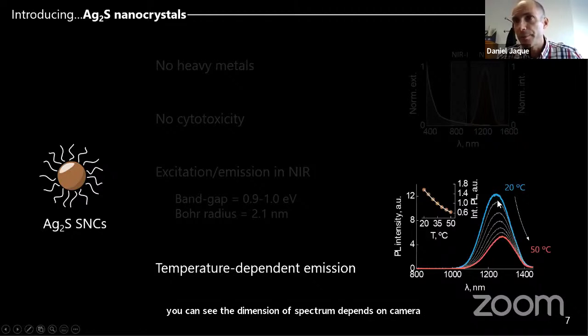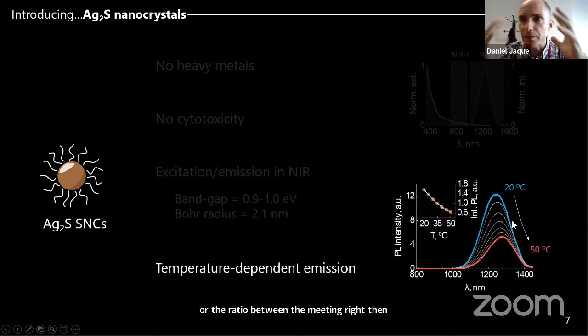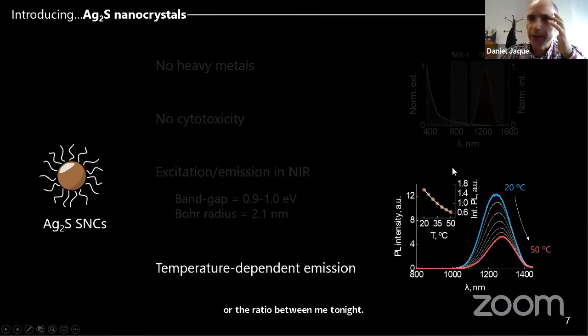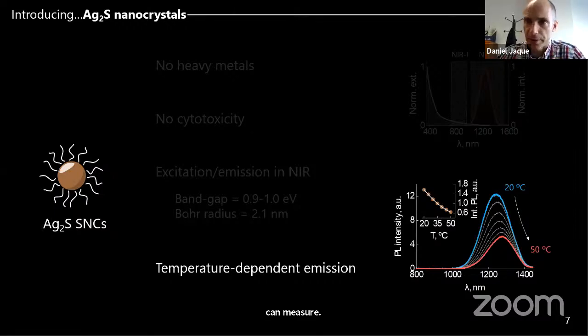So you can measure the intensity, you can measure the peak position that also changes with temperature, or the ratio between emitting light. And then you have the emission spectra of these nanoparticles. You have this calibration curve that you have here. You can measure the temperature of the nanoparticle. Okay, so they are very good emitters, and also they are quite good temperature sensors. Okay, let me illustrate what kind of things you can do with these silver sulfide nanoparticles.